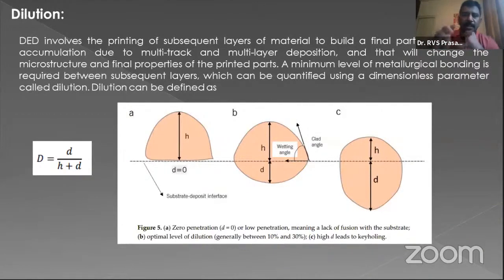And then dilution is also a very important factor in direct energy deposition, because when you are depositing layer by layer, if you do not have good dilution, then bonding between the two layers is not possible. For example, in this equation, dilution D equals d divided by h plus d, where h is the melt pool height and d is the depth of the melt pool which goes into the previous layer. Usually people consider 10 to 30% dilution is required for proper bonding between the two layers. At the same time, too much dilution is also not good. So one has to optimize to 10% to 30% dilution, which is required for proper bonding between the two layers. So this is also a very important factor when you are considering direct energy deposition.